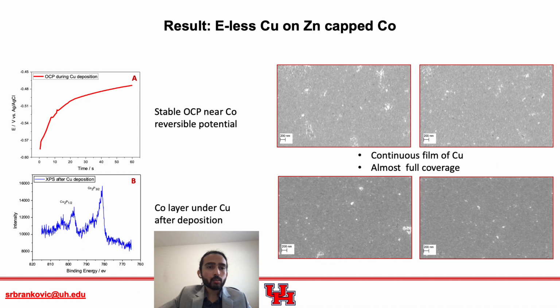Now I would like to share some of the experimental results for this project. The graph here on the left side of the screen shows open circuit potential during the copper displacement or copper deposition process. And as we can notice, initially open circuit potential is low and it increases, but the final value of the open circuit potential at the end of 60 seconds is stable near cobalt reversible potential. So with this, we can be sure that since potential is less than cobalt reversible, we are not going to etch out cobalt from the system.